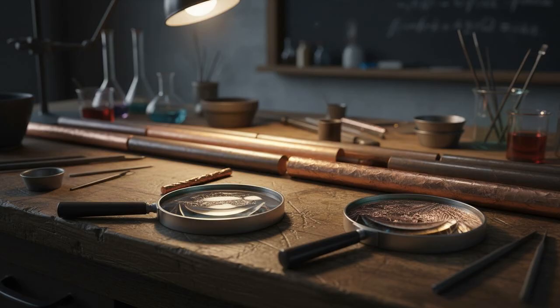For mass adoption, we need cheaper materials. Copper-based shape memory alloys, specifically copper zinc aluminum or copper aluminum manganese, are the budget-friendly contenders. They use much cheaper raw materials and are easier to machine than Nitinol. Some single-crystal copper alloys demonstrate huge latent heat capacities. The downside is that they are generally more brittle. While Nitinol can withstand millions of cycles of squashing, copper alloys tend to crack sooner. However, recent advances in adding elements like manganese and using single crystal growth techniques have improved their durability significantly.